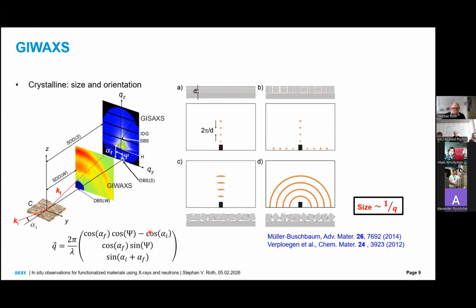Here's the full scattering vector, vector Q, taking into account that we have an incident angle, a finite exit angle, and an off-detector angle leading to diffuse scattering. And of course, the size we measure in real space is inversely proportional to the size we see in reciprocal space. Size is proportional to 1 over Q.